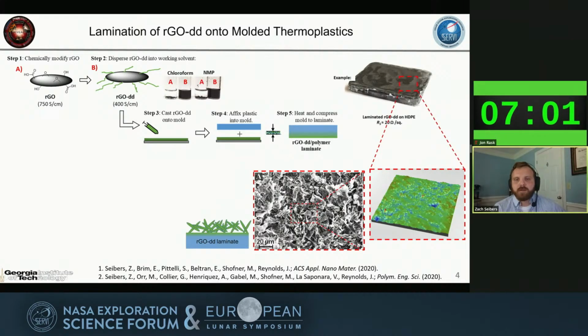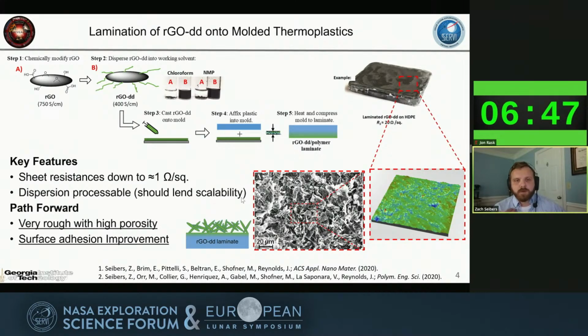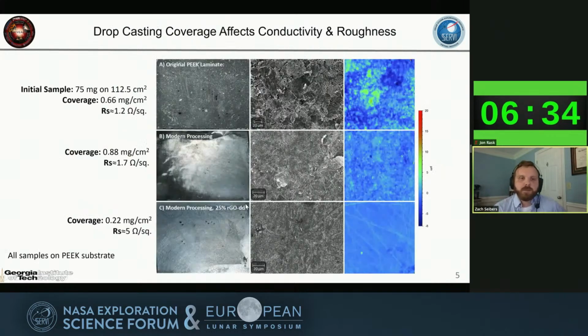And in this SEM here, you can see that while the sheet resistance of this material is less than 20 ohms per square in general, there are these void structures. That has implications when we think about lunar dust and space applications. So the key features of these films are that we've got a scalable and very electrically conductive solution to the problem, but we have this roughness issue. And that's what I'm going to talk about in these next few slides.